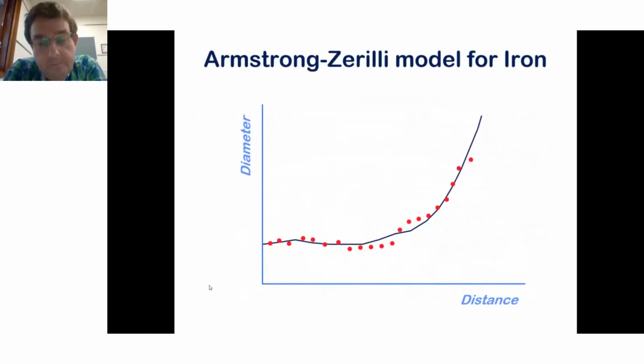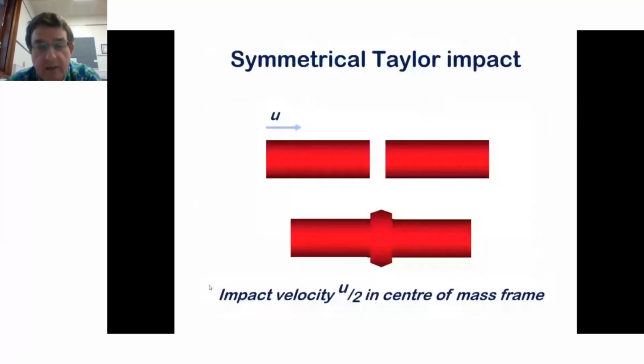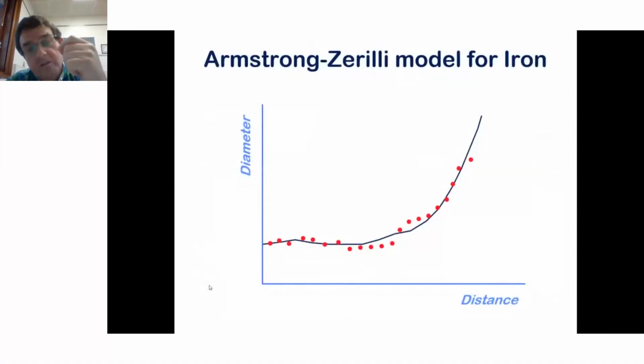People tried to model this, and Ronald Armstrong and Frank Zerilli came up with a model for the deformation of iron using dislocation mechanics. So now we're bringing in some microstructure, some mesostructure, some crystal-sized structure. We're bringing dislocations into our model. This model is quite widely known, and it was very good at predicting the shape of a rod like that, what the shape of the sample is, and you could compare the diameter of the rod with distance along the rod. The dots are the experimental data. The black line is the prediction from the model. It looks pretty good. You can go home and say, I'm happy, I've explained this data.